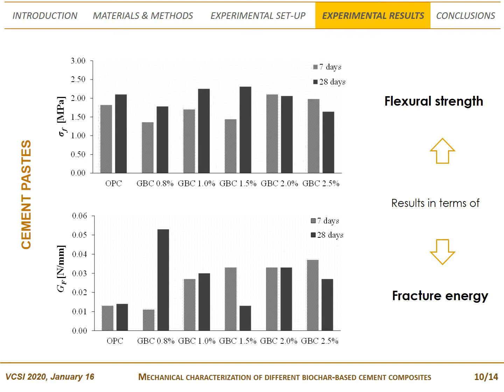Turning now to the results, for each cement paste batch, flexural strength and fracture energy both at 7 and 28 days were determined. Each batch was composed of 4 specimens and the values reported represent the mean one. It can be recognized that the batch with the lowest percentage of biochar shows a degree of flexural strength comparable to the plain cementitious paste, both at 7 and 28 days. On the contrary, for biochar addition of 1 and 1.5%, it can be noted that the values differ between 7 and 28 days. In the case of 7 days curing, there is a decrease in flexural strength, while at 28 days a significant increase compared to the reference samples is observed.